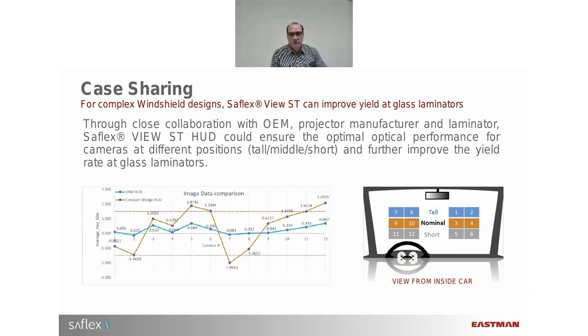Here is an example of a real case where you see the field of view is becoming bigger. Multiple cameras are used to verify what is the image, what is the ghosting, where you measure the difference between the first image and the second image. And for example, the nominal driver is specified by camera 3, 4, 9, and 10. And the maximum allowed deviations are specified by the dotted lines. So you see it's nicely in.